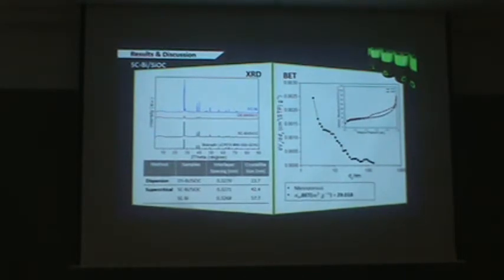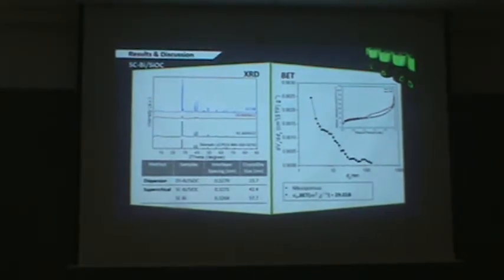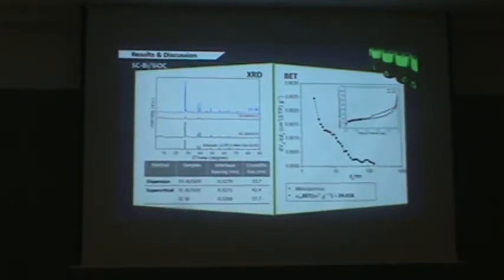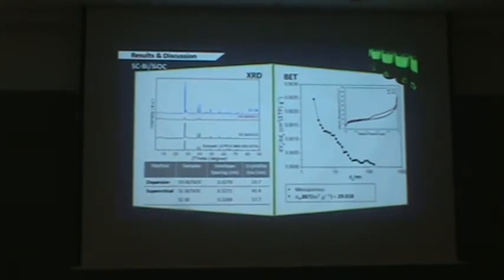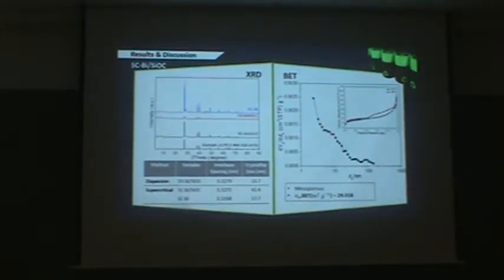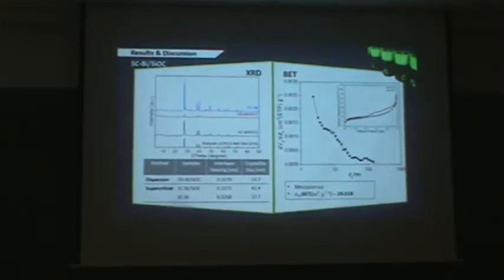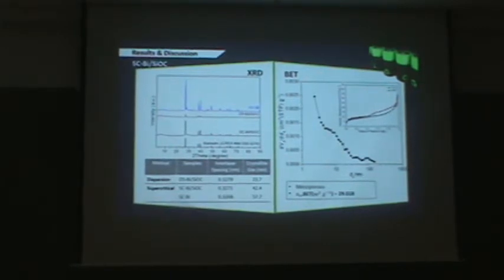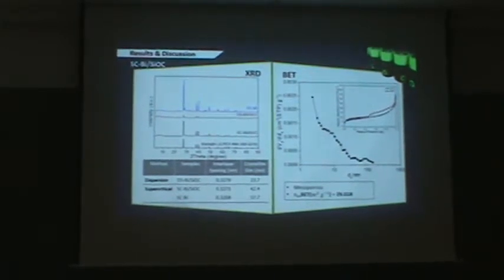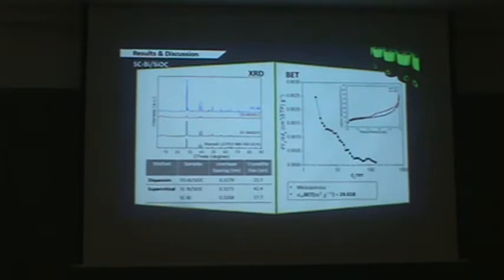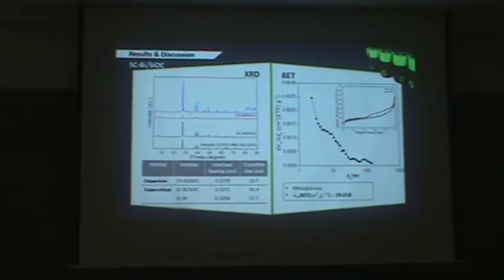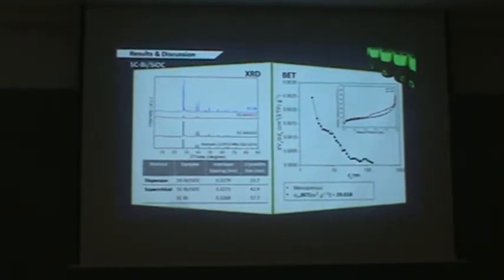For the results and discussion, our sample, supercritical bismuth silicon oxycarbide, is denoted as SC bismuth SiOC, while SC bismuth is only the bare sample without silicon oxycarbide coating. As you can see, the crystalline size is quite small, 42.4 nanometers, compared to the one without the SiOC coating. And even from the BET data, it can be seen that we have a mesoporous structure.